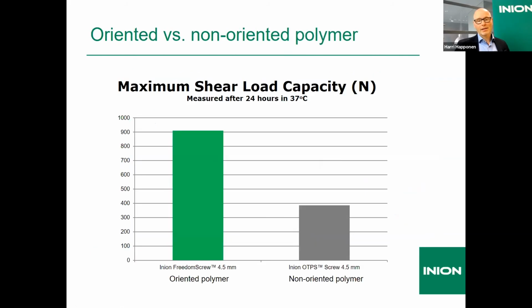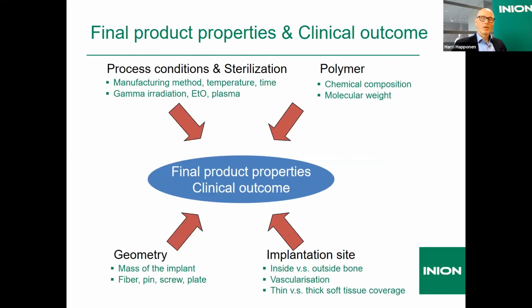Here you can see a simple example also how much orientation can improve the strength. This is 4.5 millimeter screw made out of non-oriented polymer. And this is the Inion Freedom screw, same size, 4.5 millimeter, made out of oriented polymer. And we can more than double the shear load capacity by doing the orientation for the polymer.